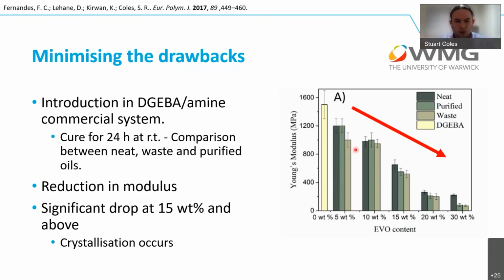With this particular oil mix, one of the things that we found pretty much straight away, if we look at the Young's modulus, is that when you add some vegetable oil based content in, across the board the Young's modulus goes down. Absolutely not a surprise. We're adding effectively a material that is a known plasticizer into a system, and we get a reduction in the modulus. That is absolutely what we'd expect, but we wanted to go through that process just to ensure that it did interact and it cured and it still formed polymers. We weren't necessarily getting significant leaching out of the oil, and the vegetable oil was being incorporated into that polymer network.